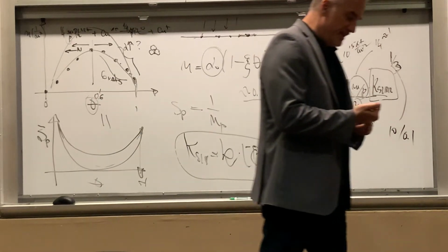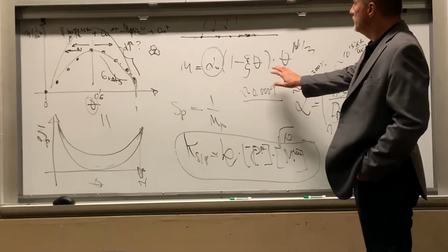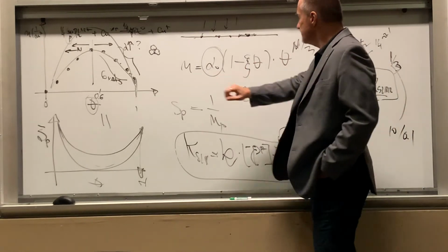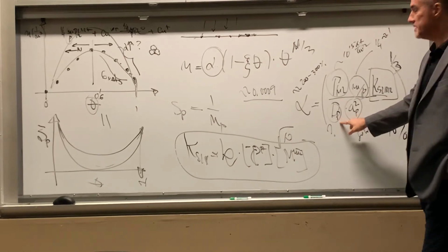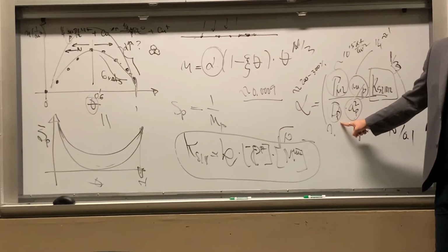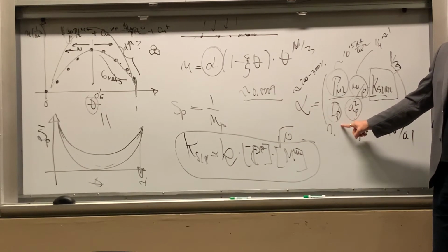All right, now what I didn't tell you is why this really works. Why is this 2D? Well, it turns out when you do the model fit and you extract this alpha, you can get the value of the diffusivity of your depositing atoms, which in this case, let's say, is platinum.